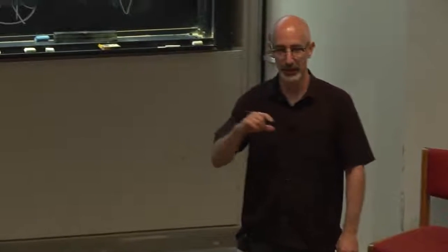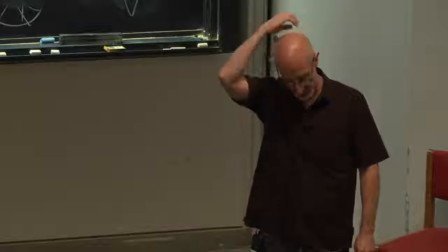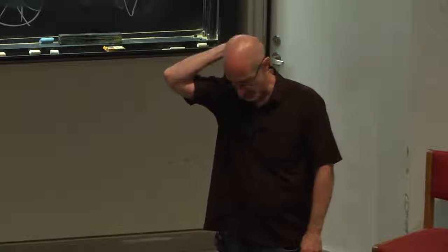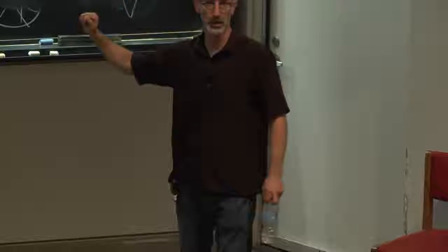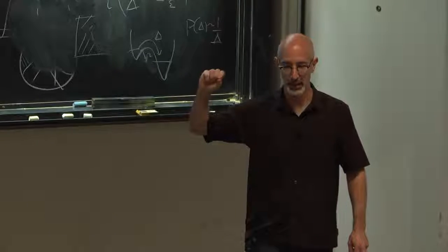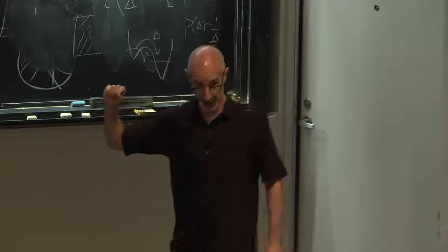Yeah, so a lattice glass model is a model that at first sight seems very much like a facilitated model, but instead of basing the motion on a dynamical rule, you base the allowed motion on a configurational rule.